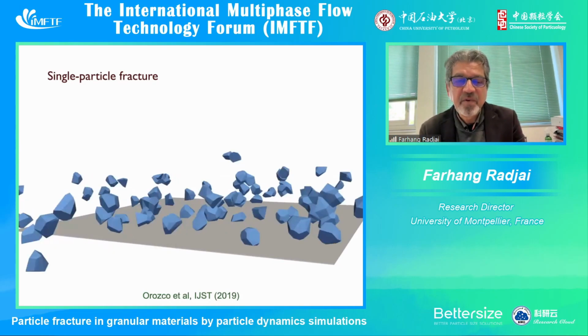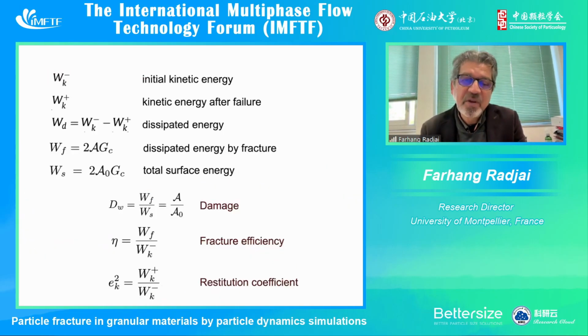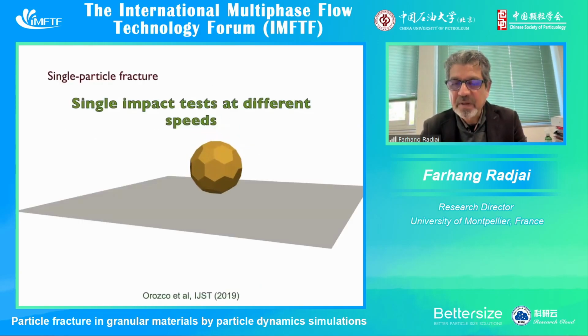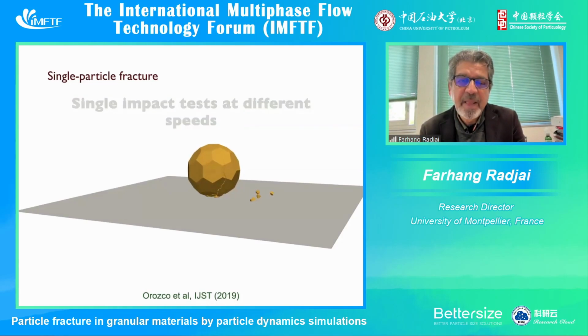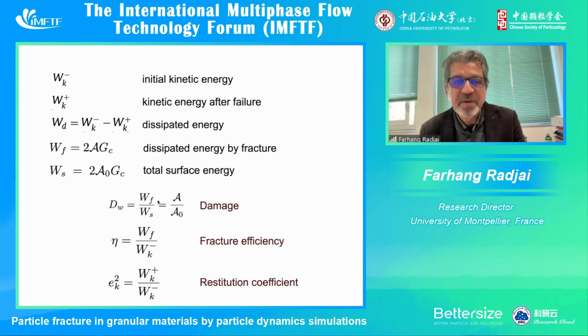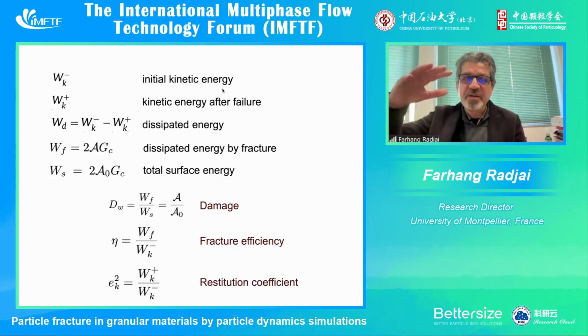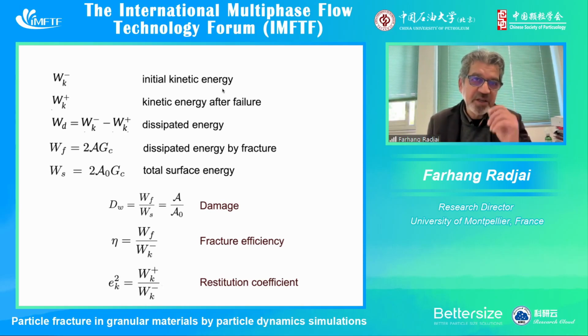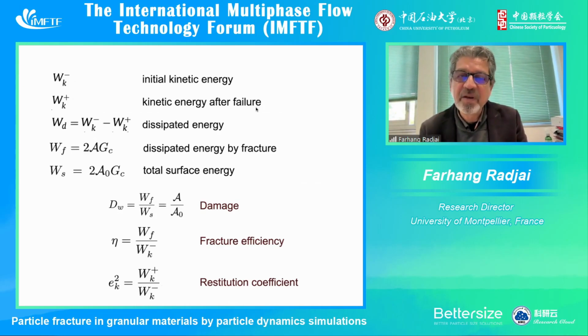And we analyzed different quantities by using, of course, a large number of fragments, for a fine discretization of the particle, such as damage. So, for example, basically we have initial kinetic energy, which is the impact energy, and kinetic energy after failure, because the fragments can have a finite velocity after impact. We have dissipated energy and dissipated energy by fracture only, which depends on the fracture energy, GC, and the total surface energy generated, which is WS.